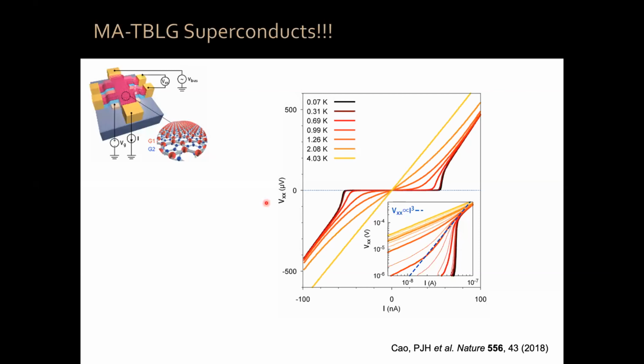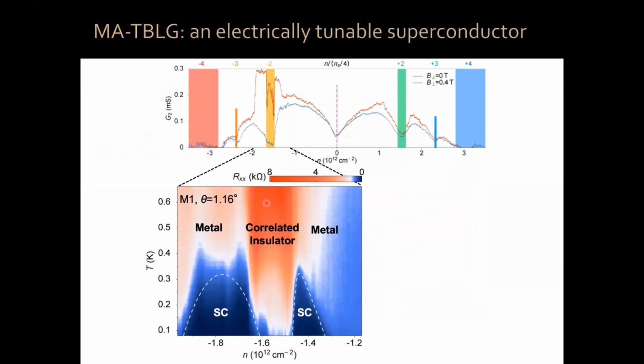Now, the nice thing, as I told you earlier, is that we can vary the density of electrons in our system. So what we saw is that if you look at the resistivity as a function of temperature and charge density, you have, at 2 holes per moiré unit cell, this correlated insulator behavior. And then as you dope with more holes, you have a superconducting dome. Blue means superconductivity, okay? As you dope with electrons, you have another superconducting dome.